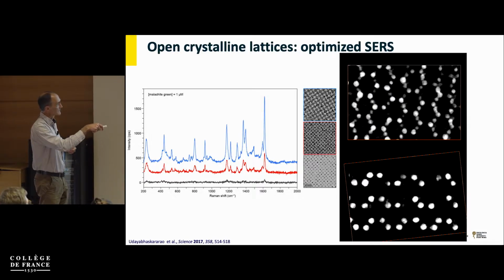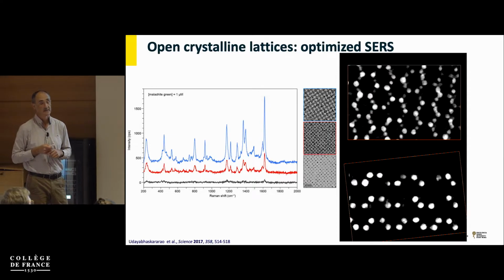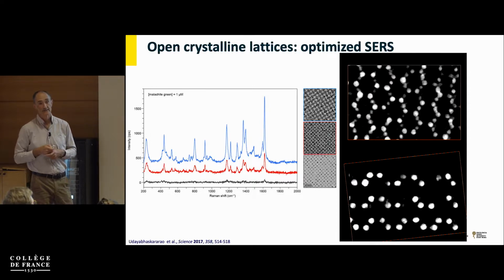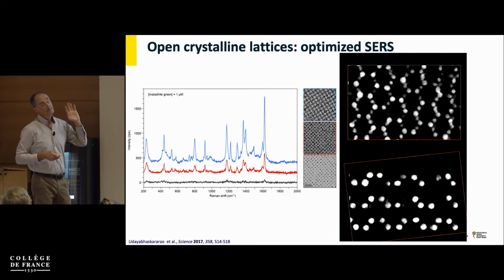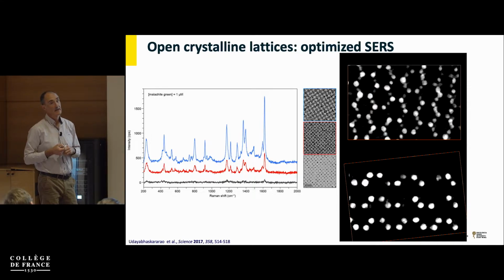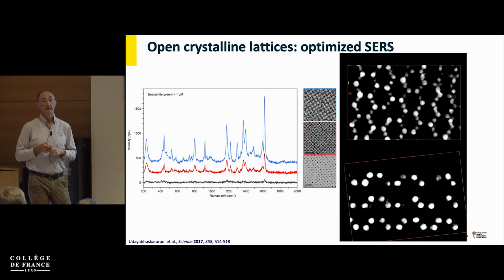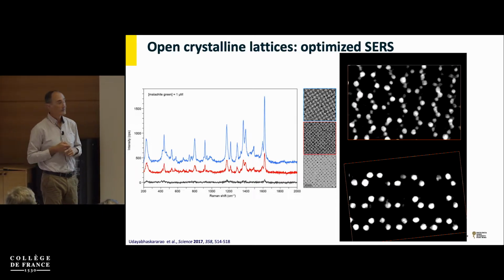For this sort of, I think it is a tri-layer, you get already a decent surface-enhanced Raman signal. And then if you increase the number of layers, then you get much better sensitivity. Now, this unfortunately can only be done in very small sizes, and it's, I would say, a bit complicated to obtain properly. So there are other ways of making well-organized assemblies of nanoparticles.